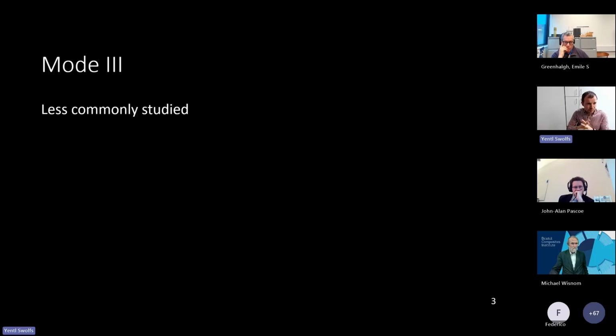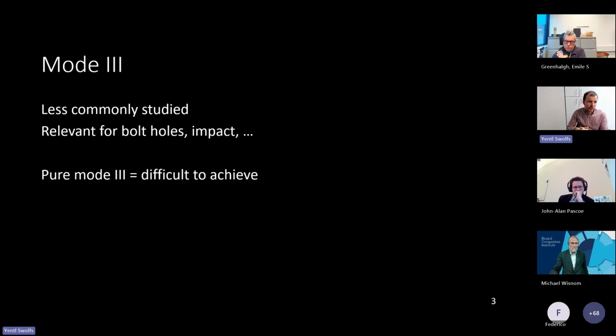Starting off specifically with mode 3, this is probably the least commonly studied of all the different interlaminar fracture toughness properties we can study, but it doesn't mean it's not relevant. It does happen around bolt holes in certain impact loading scenarios, in real structures. So it is still important that we can study it, that we understand what's going on. But in general, it tends to be very difficult to achieve a pure mode 3. Not a single test is really able to fully reproduce only mode 3 without having some, for example, mode 2 attached to it.